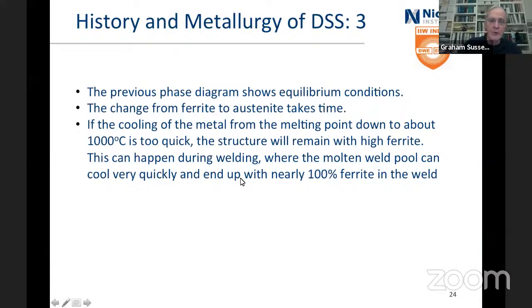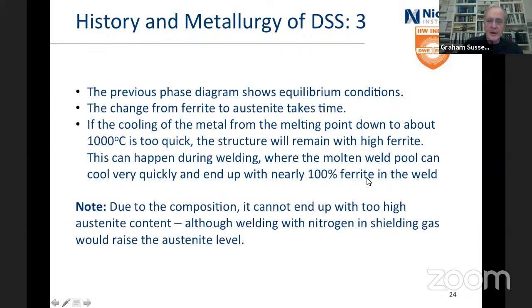The molten weld pool can cool quite quickly, especially if you're welding something thin, and you end up with nearly 100% ferrite at the weld. That's not good. Because of the composition, you can't get too high austenite, although if you welded with nitrogen in the shielding gas, then yeah, that'd raise the austenite levels quite significantly.